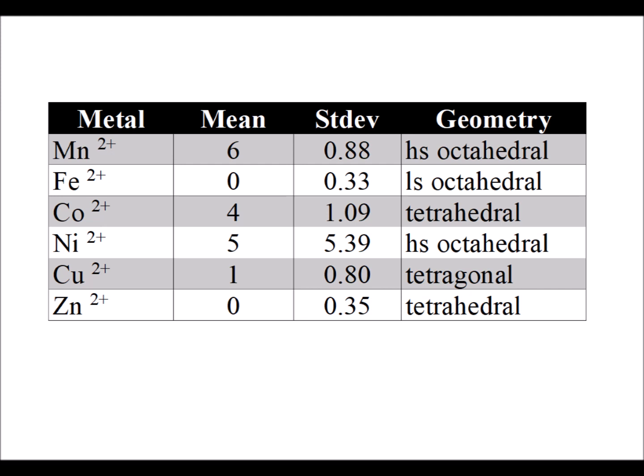So in summary you notice that for example the manganese two plus is a high-spin octahedral. The iron two plus is low-spin so it has no unpaired electrons. We see a similar situation for zinc two plus. We know that it's going to be tetrahedral. It's going to have no unpaired electrons. So those in particular are very nice test of our experimental methods to show that it gave the expected answer for a situation where we already knew what the magnetic state was going to be. Also we're able to show that there was a nice correspondence between the results of our calculation using density functional theory and our experimental results that we did from doing the actual experiments with the different metals.